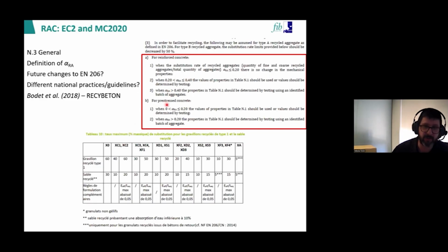For pre-stressed concrete, everything is slashed by 50%, simply because there were not sufficient results to back it up, although the effects on the concrete itself should not change. And this is for type A aggregate, the recycled concrete aggregate. If you want to go to mixed, you again reduce everything by 50%. A lot of it was based, and the Annex N as well, on research done within a French national project called RECYBETON. Yeah? So they actually provided different separate substitution ratios for coarse and fine aggregates that we try to average out